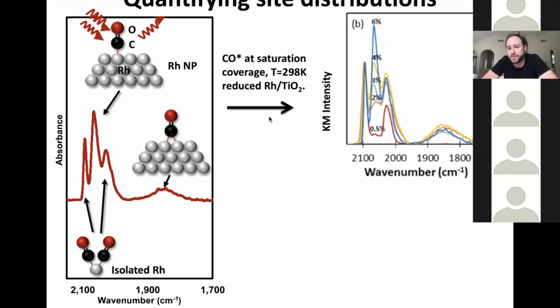We did this measurement for the series of materials that we had made, from 6% rhodium down to 0.5% rhodium. What you can see here is that at 0.5% rhodium on TiO2, the primary bands are these two bands right here, which are associated with our gem dicarbonyl species, telling us we have mostly single atoms or atomically dispersed species. As we add more and more rhodium to the sample, the band associated with CO linearly bound to rhodium particles, or this band associated with CO bridge-bonded to rhodium particles, grows, telling us that a higher fraction of the exposed sites are on rhodium particles.